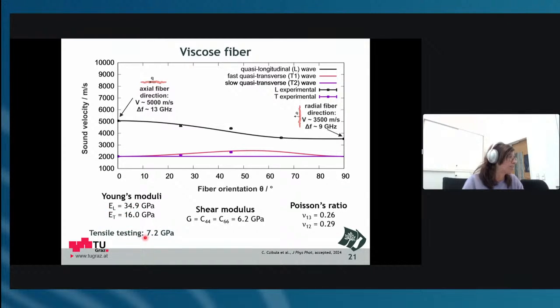I did some tensile testing on the same fibers, and we get around 7 gigapascal. And in the transverse direction, with AFM nanoindentation, you would be around 4 to 5 gigapascal. The shear moduli are about a factor of 2 higher than what we got from torsion testing of wood pulp fibers. And the Poisson's ratios are really hard to tell because there are not so many measurements out there, mostly assumptions. But we did something on pulp fibers before, and we were kind of in that range. But at least it's a full characterization.